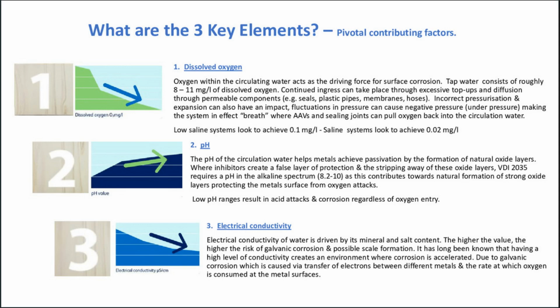Fluctuations in pressure can cause negative pressure, so that's an under pressure, making the system in effect breathe, where air vents and sealing joints can pull oxygen back into the circulation water. So if we look at low saline systems, we're looking to achieve 0.1 milligram per litre, and saline systems look to achieve 0.02 milligrams per litre.